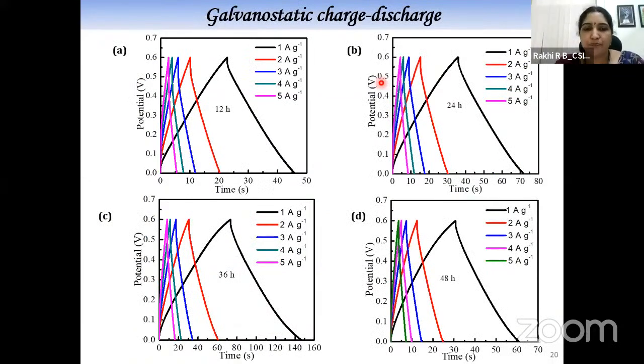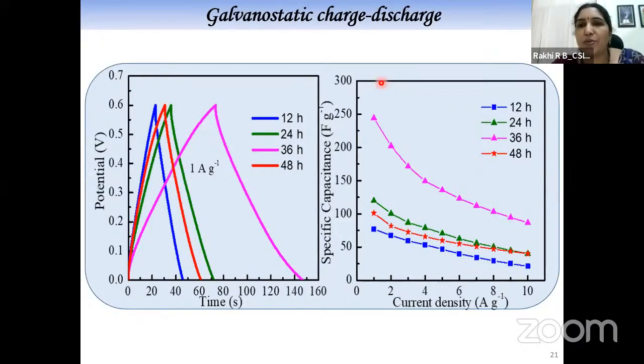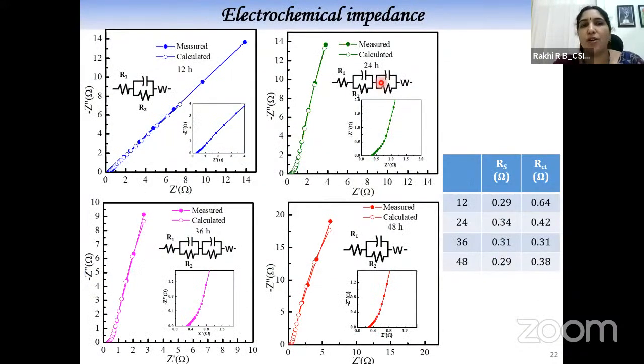Then we have done the galvanostatic charge discharge measurement. By the way, I didn't mention what the energy storage mechanism involved here is. It is actually a combination of EDLC charge storage as well as very fast surface redox reaction. But see the capacitance curves. This is almost triangular in shape. And here also we could get a matching performance from the CV and CD measurements. Nearly 250 farad per gram, that capacitance which occurs at 1 ampere per gram of current density we used to report.